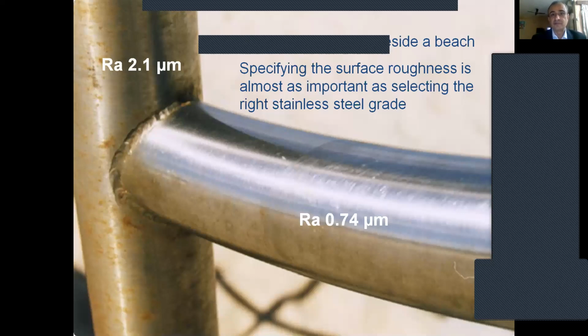So specifying the surface roughness is almost as important as selecting the right grade of stainless steel. If it is a very finished surface where the moisture cannot stay on the surface, corrosion may not occur on that. If it is a rough surface, not smooth, like an RA factor of 2.1 micron versus an RA factor of 0.74 micron, you see this point where the roughness is more, the moisture content can stay on the surface. It can discolor and then corrode.